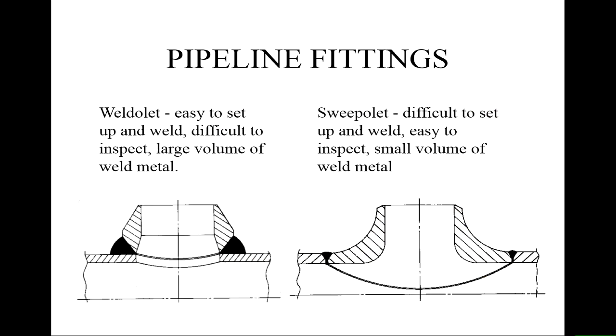So here's an example. With the weldolet, you're welding almost vertically onto the pipe. So we've got that expansion of the shape. This is the bit that welds onto the T-piece line pipe. This is the line pipe you're welding in. There's a hole here. We've got expanding metal, and we've got the line pipe, and we're just filling in the gap with the welding. So that's a weldolet. A sweepolet, we're still welding in, but the welds are now in the plane of the line pipe. They're more like the girth welds that we're going to talk about later on. And then the shape is all in the thing you're fitting in.